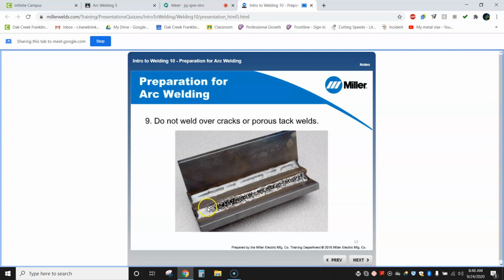This right here, this porosity would require you to grind it all the way down to the root. This you could probably get away with taking it down until it's gone. This requires a full removal of the entire weld, because if you take it to where you don't see the porosity anymore and not down to the root, you're going to end up with porosity again. I can guarantee it.